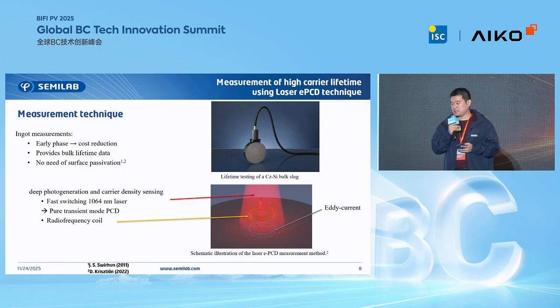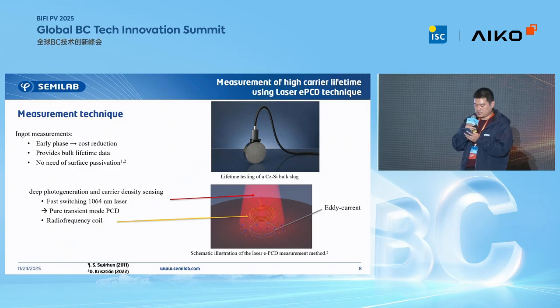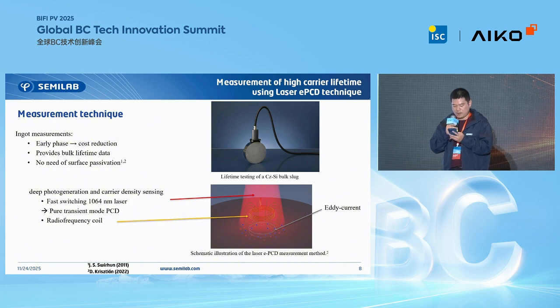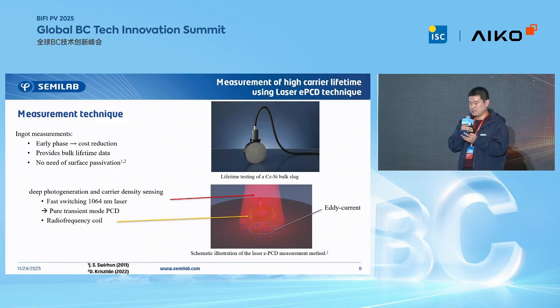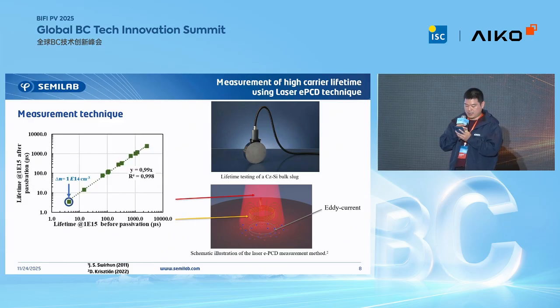The other important electrical parameter to control the quality of the ingot is the carrier lifetime. Several years ago, we introduced the upgraded version of our laser-based eddy current PCD sensor, which enabled the measurement of bulk lifetime in pure transient mode, evaluating the entire carrier lifetime range within 1 to 2 seconds automatically. And as shown in this example, it provides an accurate and reliable single lifetime value at a certain injection level.